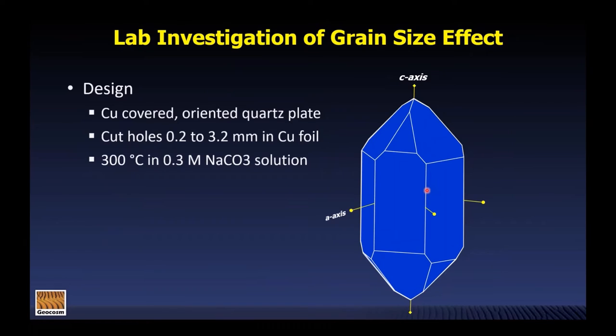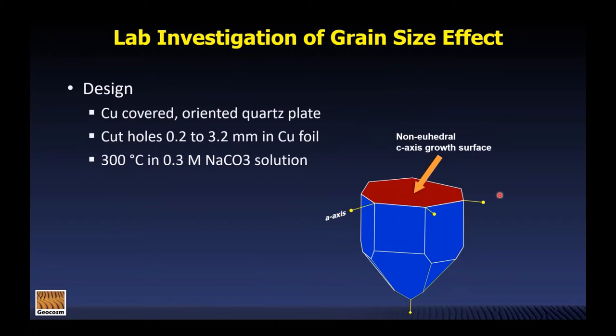And so what we did was we took a single quartz prism like this one, and we sliced it perpendicular to the C crystallographic axis, which would be the long axis of the prism. Now onto this surface, we placed a copper foil, and into that copper foil, we cut a series of holes over a size range that would include and extend beyond what we would expect for a sand grain. And so we then put this into a hydrothermal reactor that was supersaturated with respect to quartz, and we grew a bunch of little overgrowths through those holes.